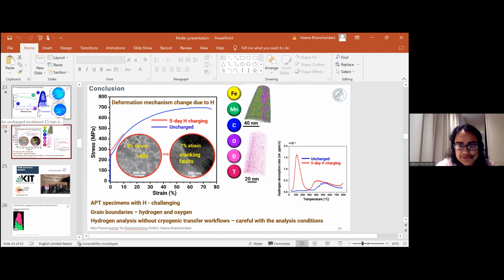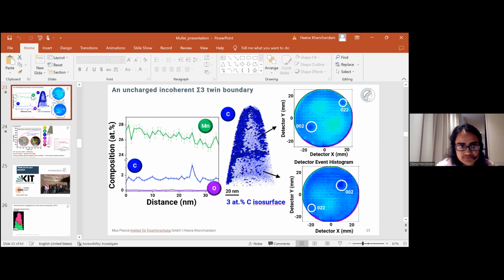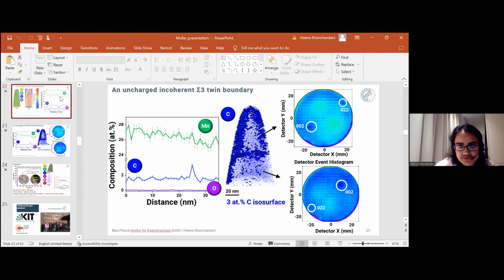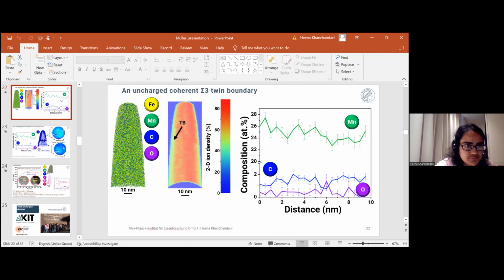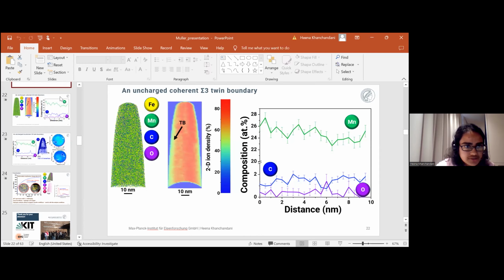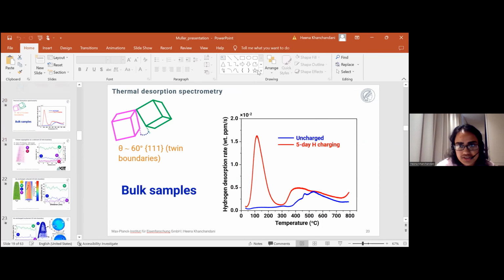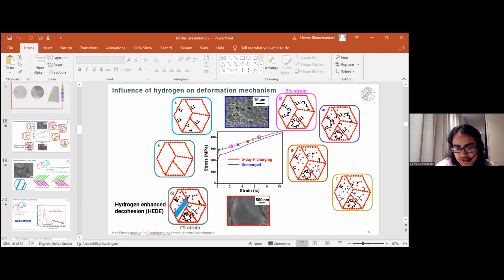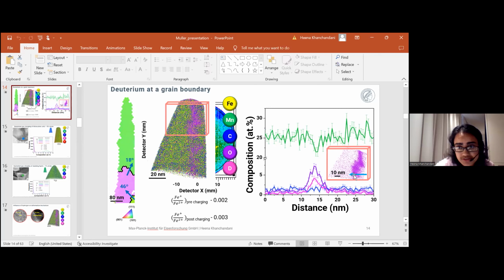Yes, in principle, there are always trajectory aberrations in atom probe. But in the segregation, more specifically? Less, no. I mean, in this case, if your question is with reference to this profile that I showed here, maybe. Yeah, so in this case, this could be the diffusion profile because the thickness of the grain boundary is like 2 nanometer, but it is also that it is faceted grain boundaries. So in the atom probe, so. Thank you.